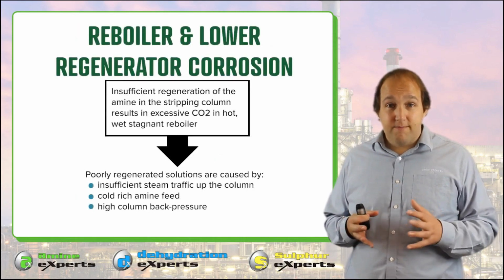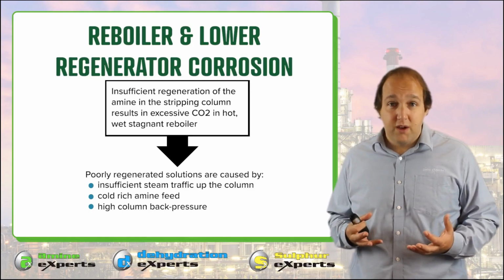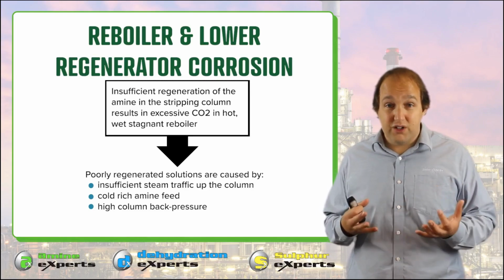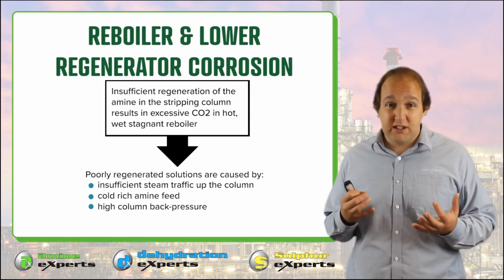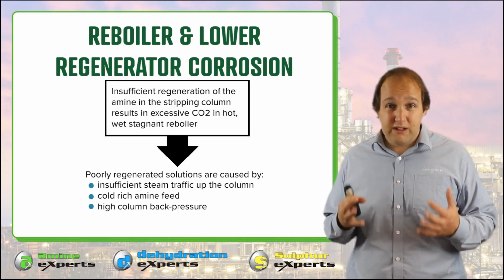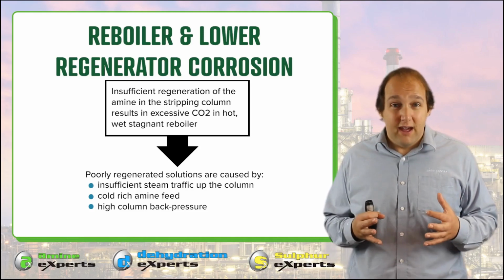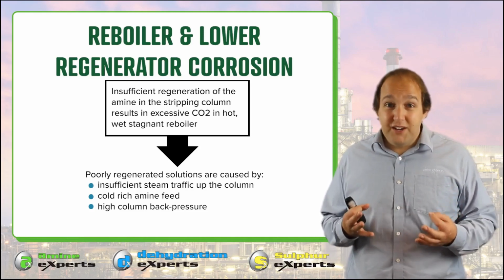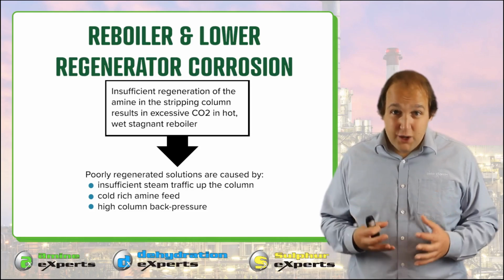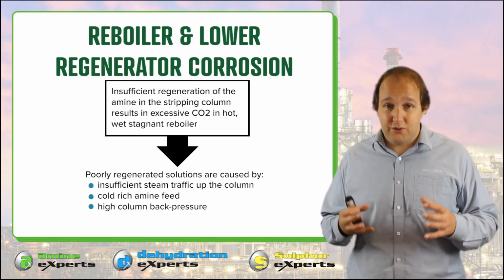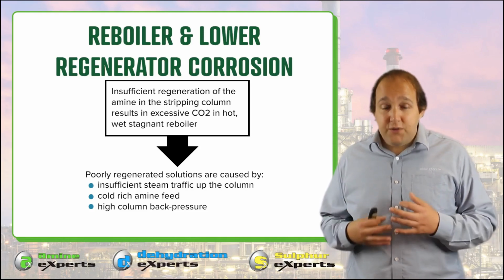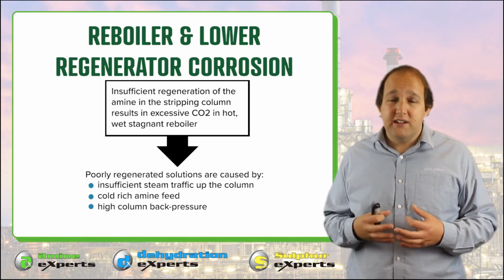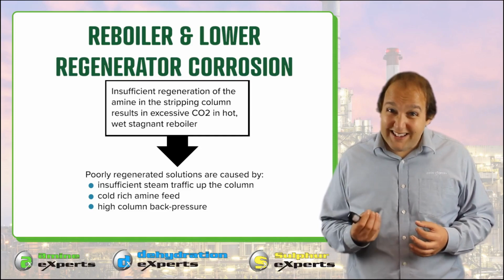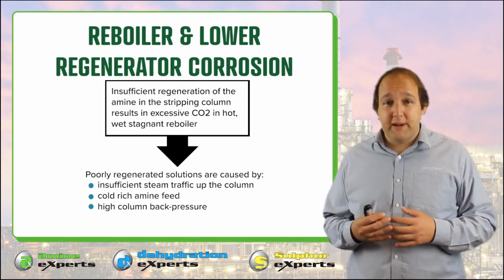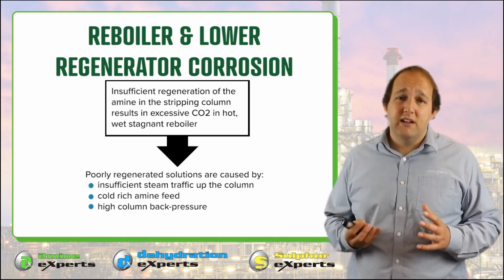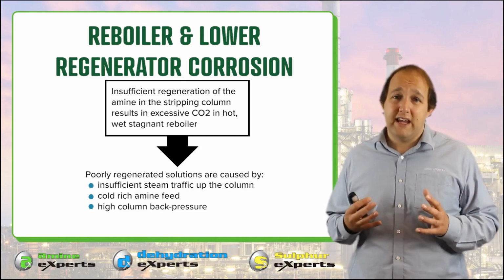So the first, and really one of the most preventable types of failures, that accounts for a large number of the production failures that we've seen, especially when there's a reboiler tube leak, hole in the reboiler shell, vapor return line, or bottom of the stripper, is what we call understripping. And that really just means that there's not enough heat duty going into the amine to regenerate it properly. So you will still have a lot of CO2 left in the amine. And even if you're on, say, a refinery amine system where there's very little CO2, the CO2 is actually a stronger acid than H2S. So you could end up stripping out most of the H2S, but you'll still be left with the CO2 in the lean amine.